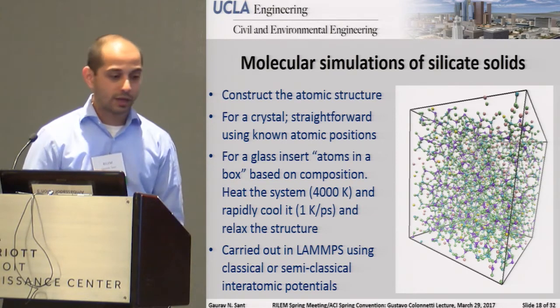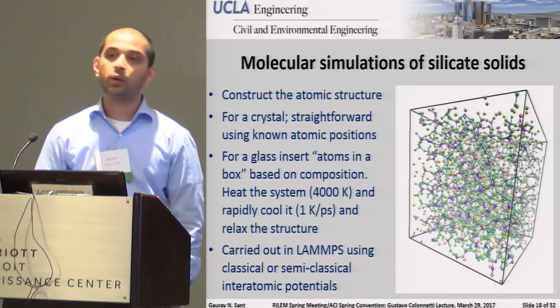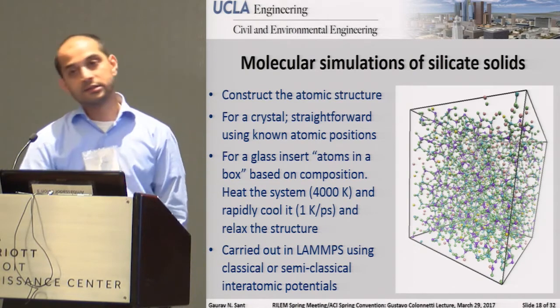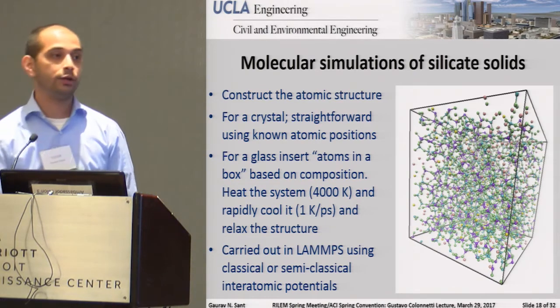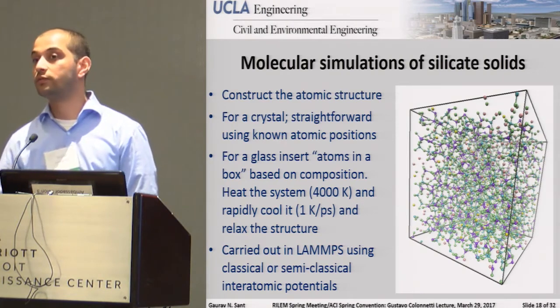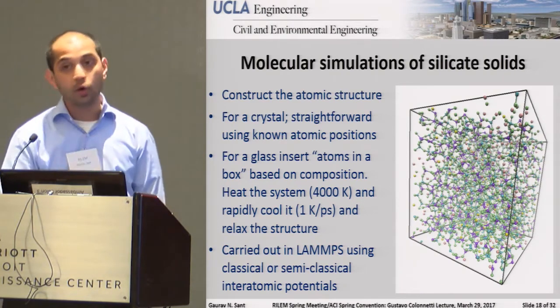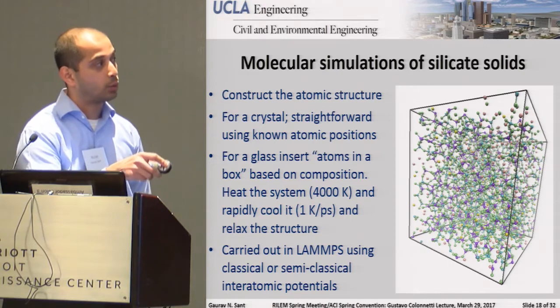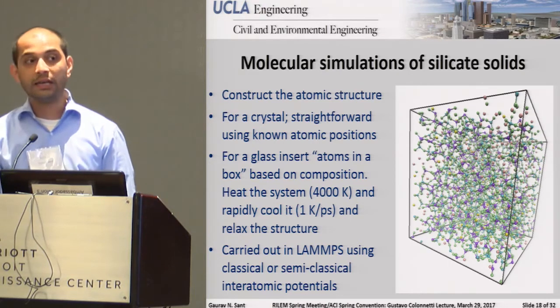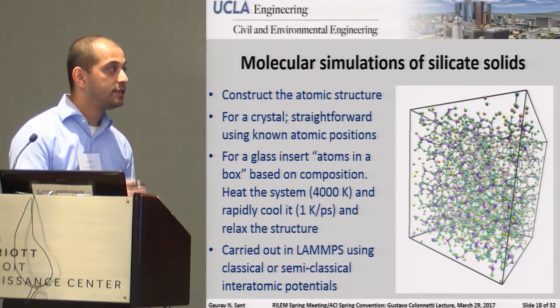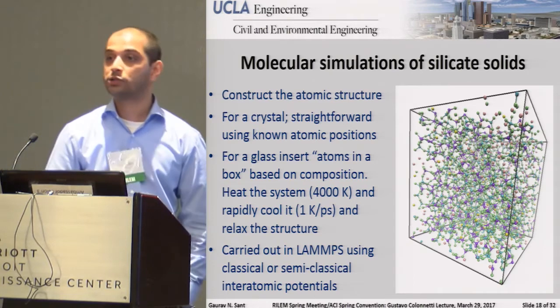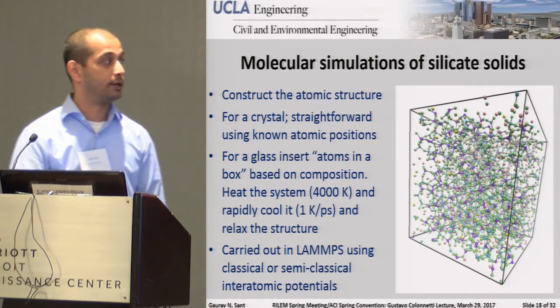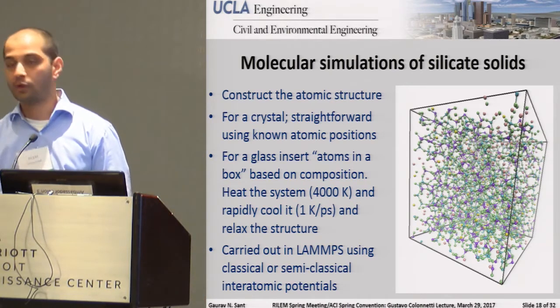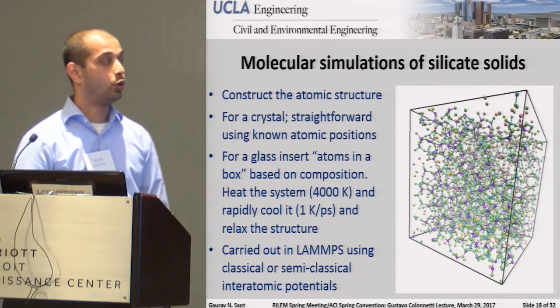So you need to go through what I'm going to call a melt-quench procedure, where you need to heat the system to, for example, something like 4,000 Kelvin. You do this so that it removes all of the memory of its initial configuration, and then you cool it. When you cool it, you're cooling the system at 1 Kelvin per picosecond. So it's incredibly fast. Now, the reason you want to do it is that if you hyperquench the system, of course, you get something which is perfectly amorphized. Once it's hyperquenched, you relax the structure, and now you've got an atomic structure you can work with.